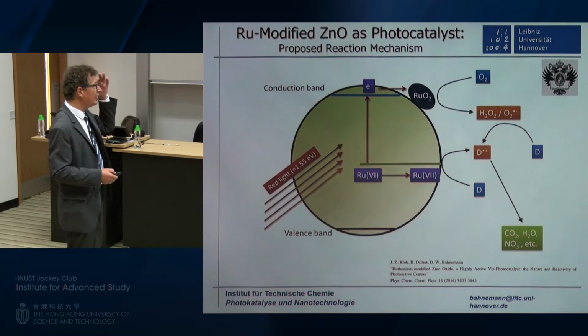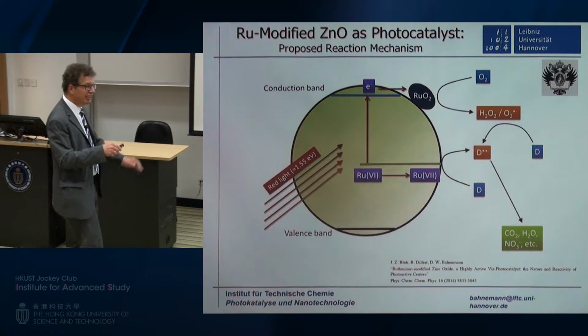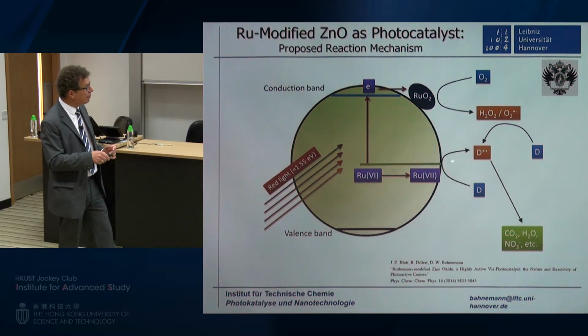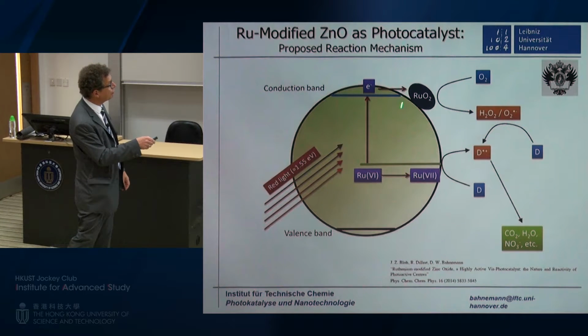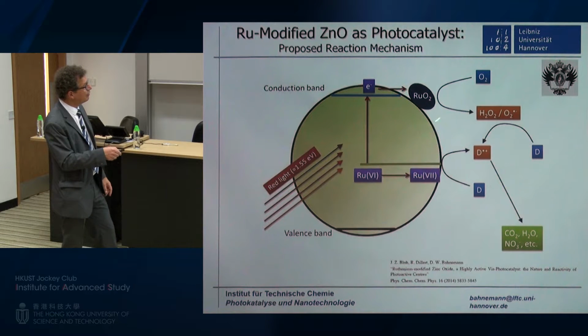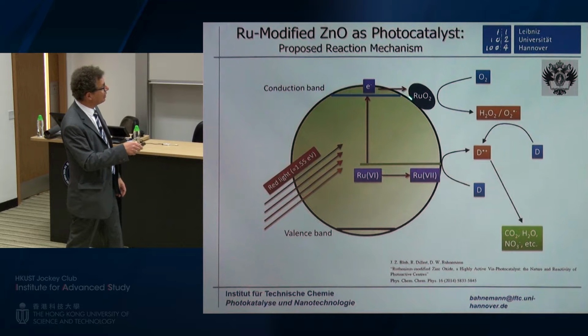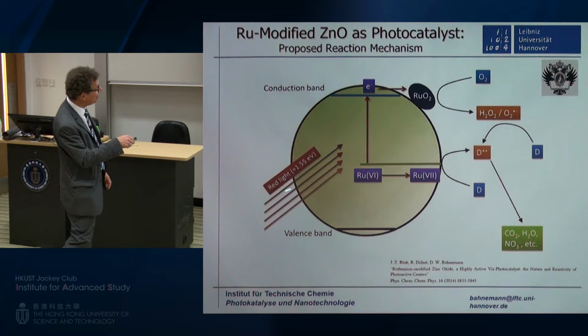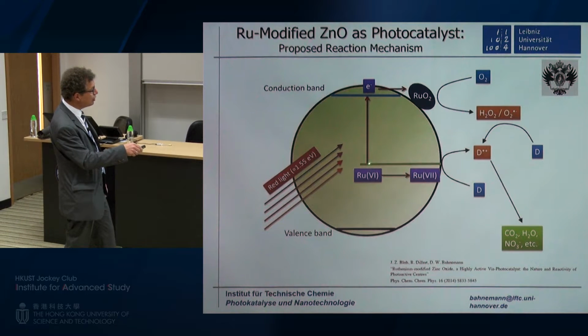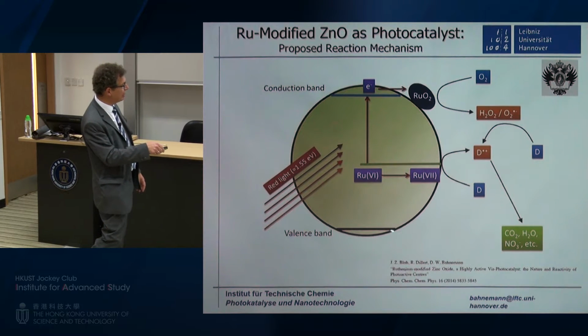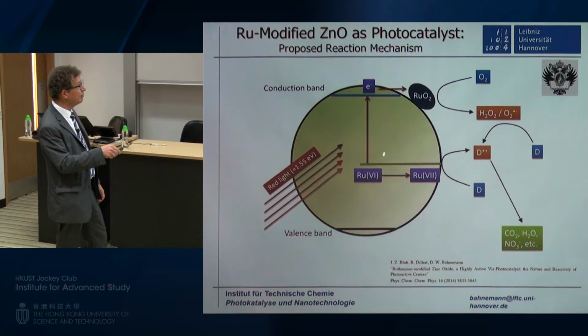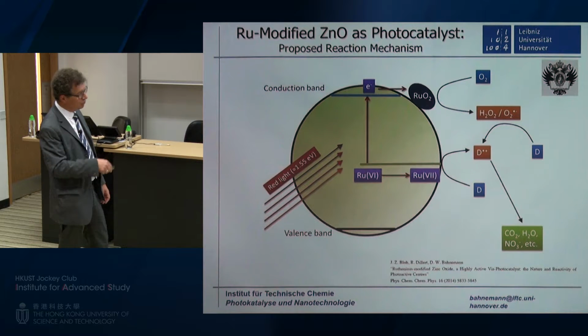What is happening here, this is our mechanism which we propose. We think that ruthenium is indeed incorporated, forming new mid-band gap states in the zinc oxide. And you also have ruthenium oxide, which is a well-known catalyst on the surface of our zinc oxide. This catalyst will act as an electron transfer catalyst, will not be involved in the photo process, but the photo process can now be induced by really red light. 1.5 electron volts is sufficient because now you can excite electrons from these filled mid-band gap states to the conduction band. So you have a process where the electron donor is oxidized by the oxidized mid-band gap states rather than by the valence band materials. That would be an interesting material indeed for visible light activity because you can utilize really red light here.